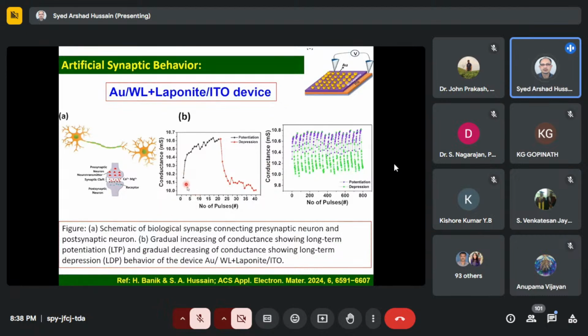Then we apply pulses of certain duration continuously. We have found that the conductivity or current across the device goes on increasing, and after a certain time it becomes saturated, or maximum current is attained by the device. That means we can say maximum memorization level. Then again at reverse polarity, pulses of suitable width, duration and amplitude are applied, and as you go on increasing the number of pulses, you see conduction across the device goes on decreasing.